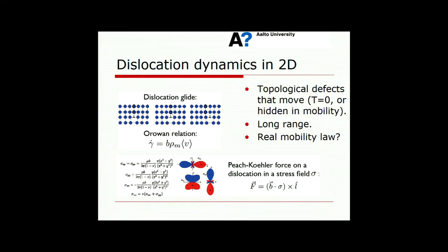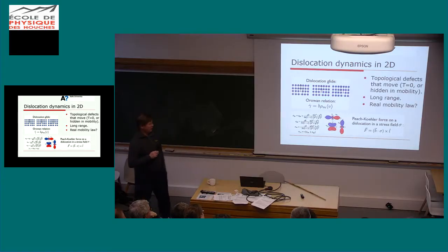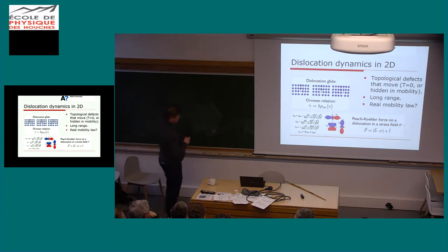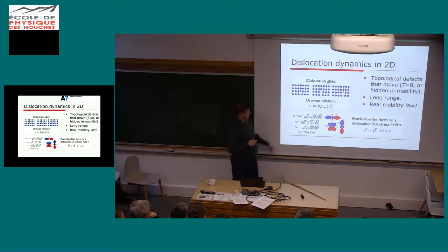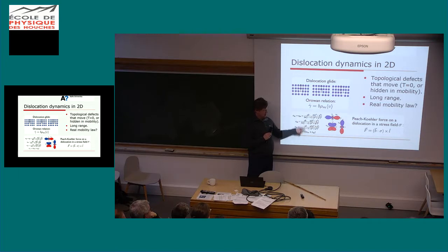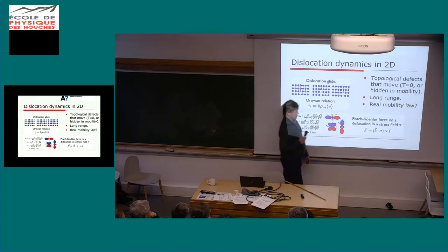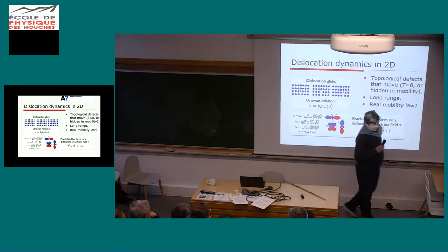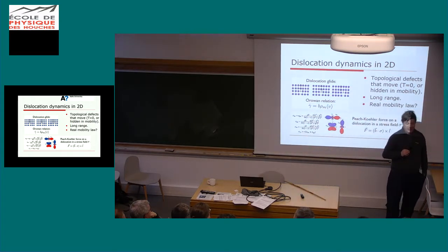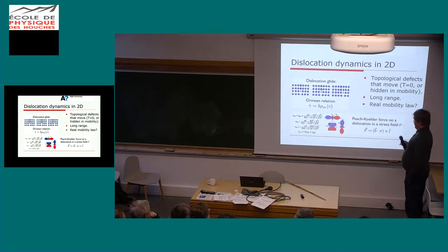so what we do then to resolve this is that we take a toy model, and I like to tell this to metallurgy people that we, as physicists, take the simplest case of an edge dislocation that you move around, and you write an equation of motion. What you have in this thing is that of course you have interactions of the usual complicated character, and this is more or less zero temperature. Theoretically speaking, at least if you want to coarse grain a molecular dynamics simulation, what you do is figure out what the mobility is for the dislocation, plug it in, you forget about temperature, and of course you can play with these things.